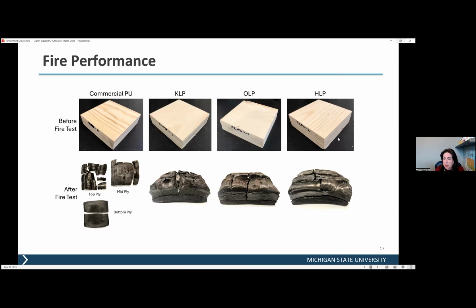And these are the samples that we sent to Forest Products Lab. These are before testing. This one is made with the commercial adhesives, and you can see the clear adhesives, and the other ones are the samples that we made with the kraft softwood, organosolv, and hydrolysis hardwood adhesives. These are the samples after the test. You can see that the ones with the lignin-based adhesives, even though they're fully burned, the adhesive was strong enough to keep them together. And the commercial adhesive samples, as soon as they opened up, completely fell apart. We knew that was going to happen because lignin is a natural flame retardant, but seeing this performance was very encouraging. Seeing that this is a bio-based adhesive and has really good fire performance or flame resistance.